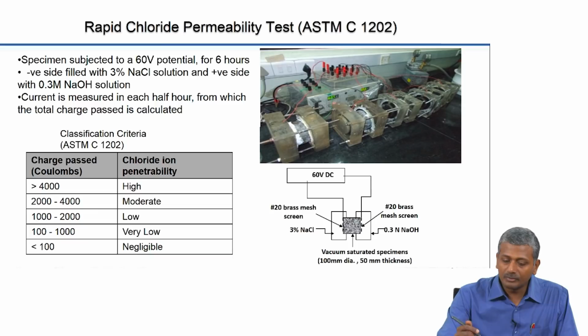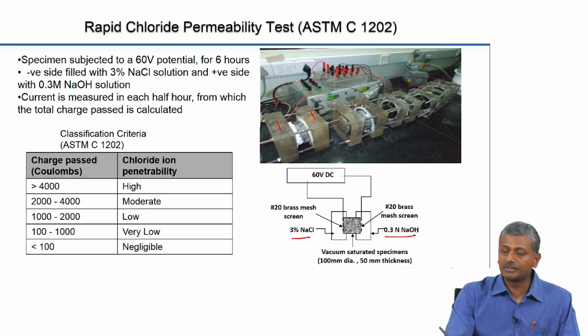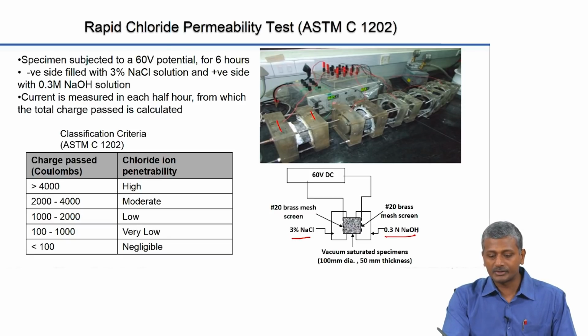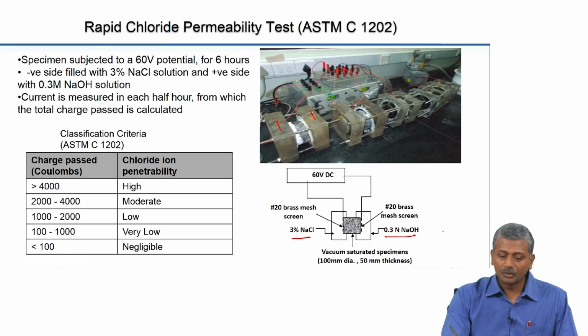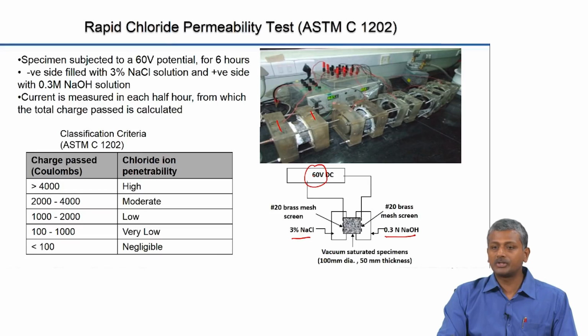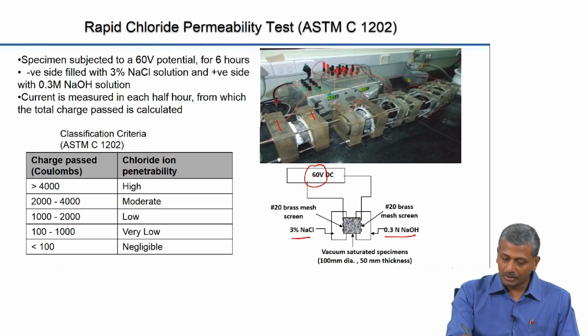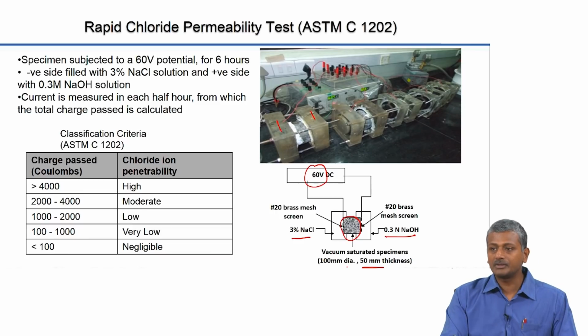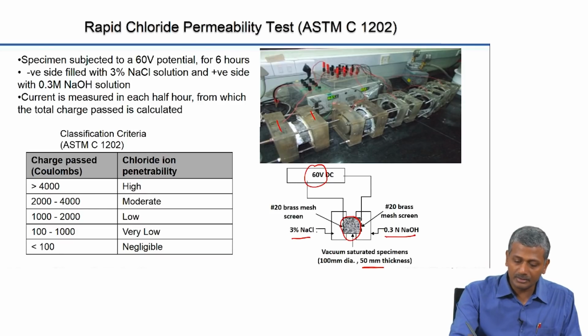So, here you have 2 cells, one is filled with a sodium chloride solution, 3% sodium chloride, the other is filled with a 0.3 normal sodium hydroxide solution, okay. And then you connect this to a power source where 60 volts potential difference is created between these cells. The concrete, which is about 50 millimeters thick and has 100 millimeters diameter, is kept between the cells. And what is it, so this is your positive side and that is the negative side.